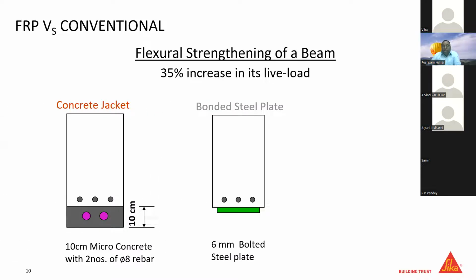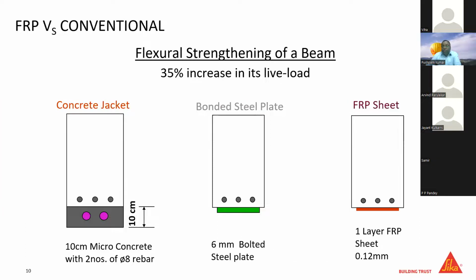The similar kind of load carrying capacity enhancement can be done with 6 mm steel plate, or the another option is one single layer of FRP, which has a thickness of 0.12 millimeter. So you can make a comparison that, in terms of dimensions, these are very effective, and this can increase the load carrying capacity of the structural member, provided it has been designed and used in the proper way.